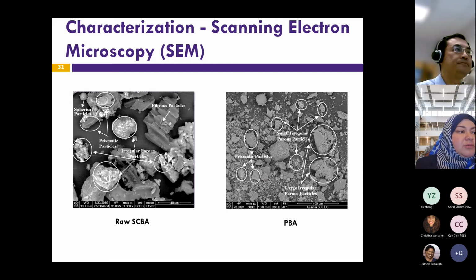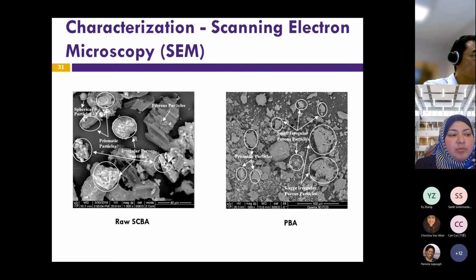This is just a snapshot, some SEM pictures for the sugarcane bagasse ash and the post-processed bagasse ash. As you can see, the sugarcane bagasse ash has some unburned fibers, irregular porous structure, and prismatic particles. When you look at the post-processed bagasse ash, you still have the prismatic particles and the porous particles, but you no longer have the unburned fibrous particles. So the unburned fibrous particles is what we get rid of by sieving. And the remaining particles are pretty much crystalline silica and amorphous silica, which indicates that we have an activity index, so it can be used as cement replacement.